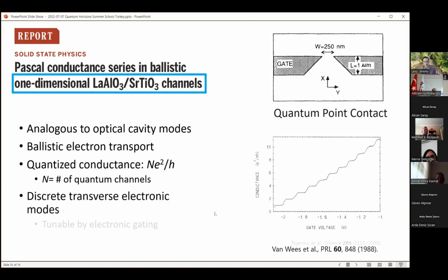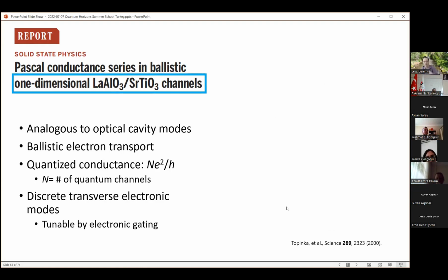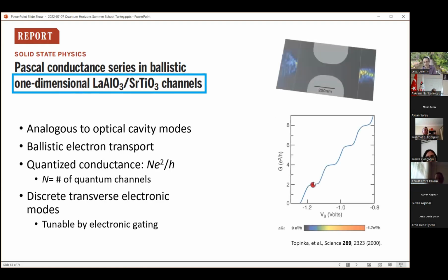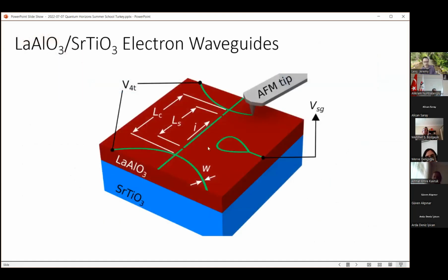And it's discrete. So what you find is that you get steps in the conduction. And these steps actually can be visualized if you have a scatterer, like from a low temperature AFM. This is beautiful work done by Bob Westervelt's group at Harvard, where they could actually image the lowest mode, which is, okay, it's a little noisy, but it's just like the Gaussian, and then there's the 2 lobes and the 3 lobes, right? So depending on how you tune the system, you can allow different numbers of transverse modes to pass through. So we're interested in creating one-dimensional electron waveguides.